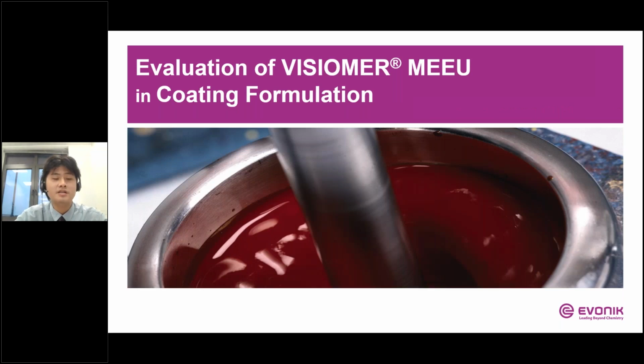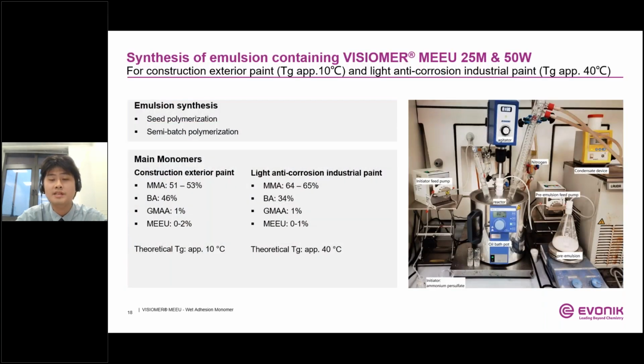And in the next part, I will introduce the performance of MEEU in two typical application directions we recommend: the construction paint and the industry paint. To this end, we have produced a series of emulsions based on the typical glass transition temperatures of acrylate emulsion in construction and industry paints. This is our guide formulation. Just adjusting the ratio of MMA and BA, we designed 5 sets of acrylate emulsion for construction paints with a Tg around 10 degrees, and 3 sets of acrylate emulsion for the industry paint with a Tg around 40 degrees.